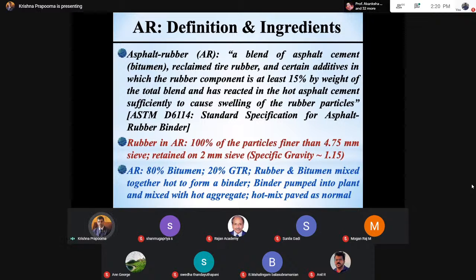But some people have been blending CRMB and using it with dense graded, which is another successful failure. I call it a successful failure because people have failed in blending that. Universally people have used the Arizona gradation, the Arizona blend, which calls for about 20% rubber inclusions by weight of asphalt cement. Let's say you have 80% bitumen, 20% rubber, that makes 100% asphalt rubber blend. And that is the number that we use when you do the job mix formula.